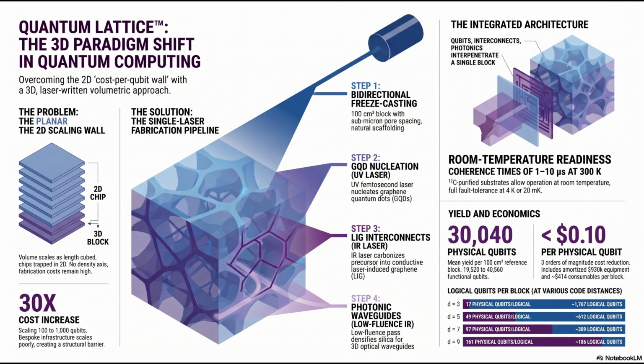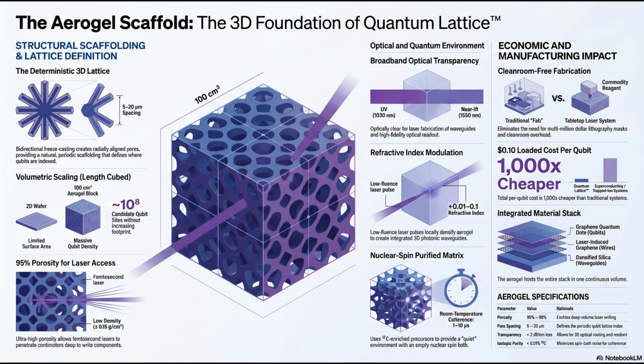That's incredible. And they aren't just drawing straight lines, right? Oh, no. The paper lists specific addressable photonic structures they can write. Y-splitters, which take one photon pulse and distribute it to many sites for clock synchronization. Mach-Zehnder interferometers, which split a photon and recombine it to measure phase shifts. And ring resonators, which act as microscopic filters to tune specific wavelengths of light. All of this operates in the 1030 to 1550 nanometer telecom band, with signal losses below 2 decibels per centimeter. And because it's a true 3D volume, they can route these fiber optics in 3D space. On a flat silicon photonic chip, if two light paths need to cross, it's an engineering nightmare of layer stacking. In this block, a waveguide can just swoop over or under another waveguide without touching it.